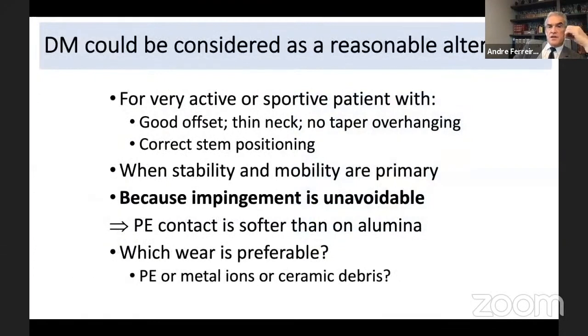So dual mobility could be considered as a reasonable alternative for very active or sportive patients with a good offset, thin neck, no taper overhanging, with a correct stem positioning, of course, and a correct cup positioning also. When stability and mobility are primary, of course, we can choose dual mobility, even if impingement is unavoidable, but to delay this contact, and because the polyethylene contact with an insert of dual mobility is softer than on alumina, and with a ceramic-on-ceramic total hip arthroplasty, there is a risk of fracture of the alumina.